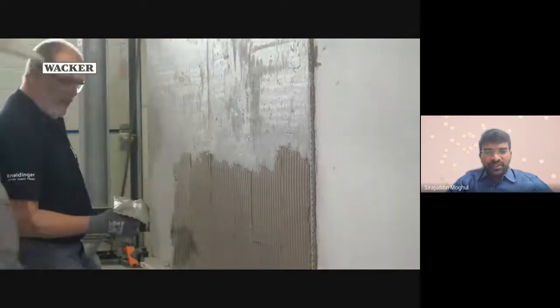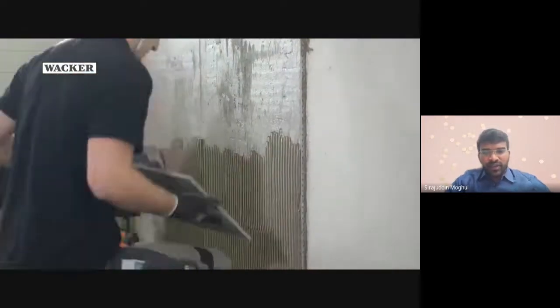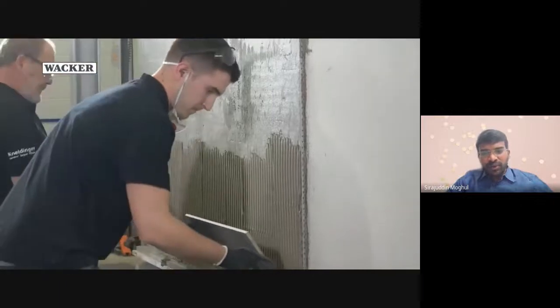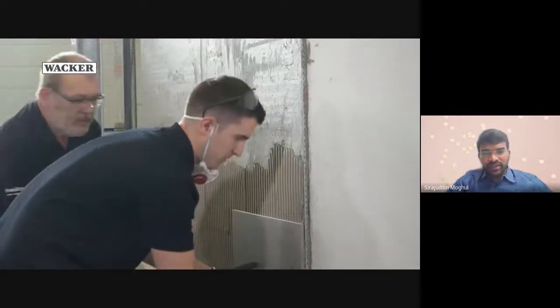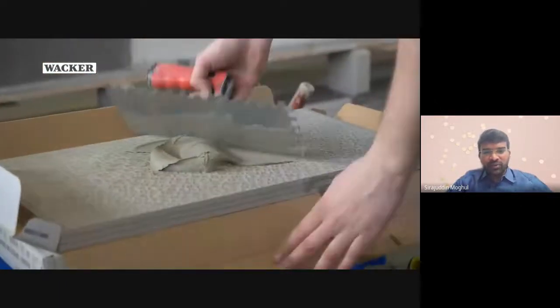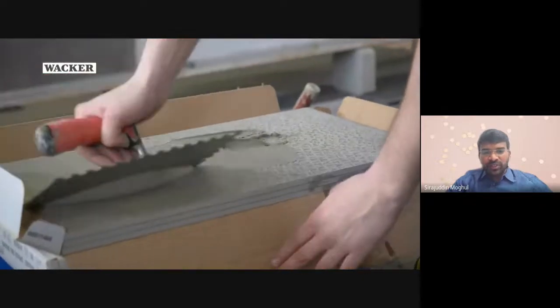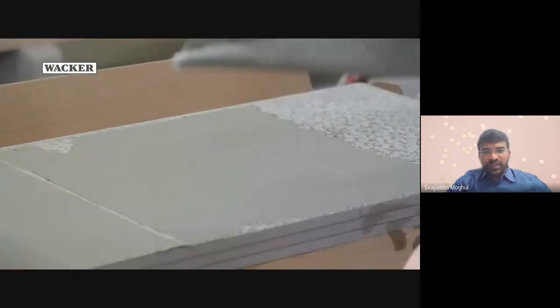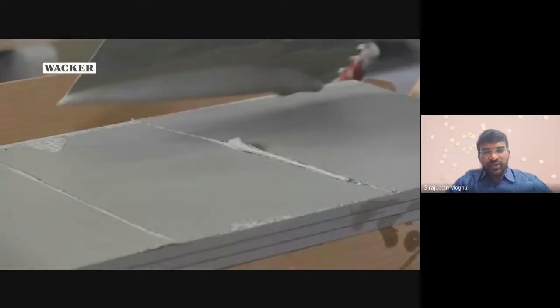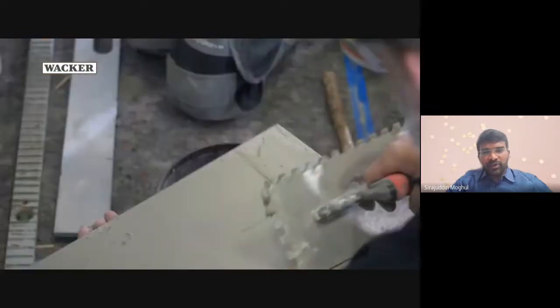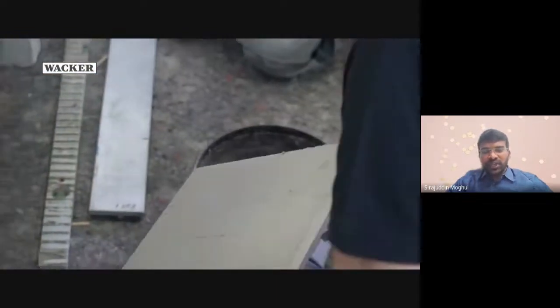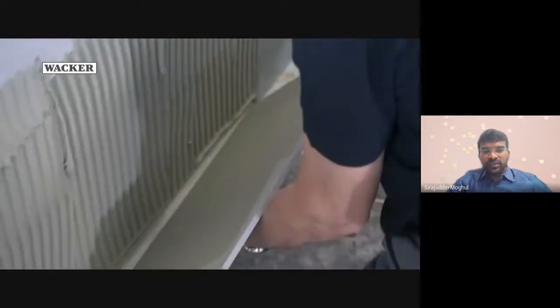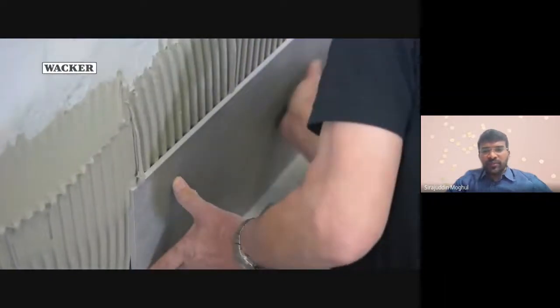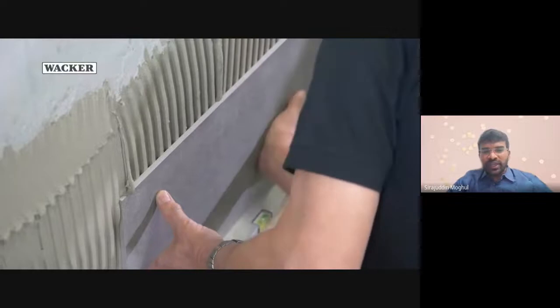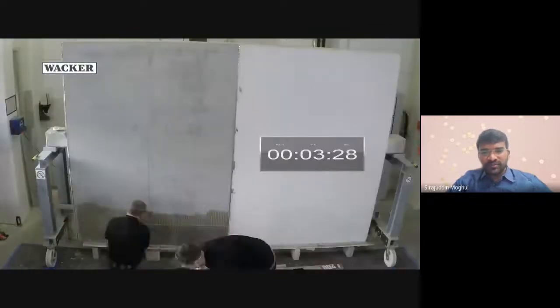And now see, this is the thin bed technology where he uses a polymer modified mortar to apply tiles. You apply the mortar with a trowel, draw notches, and do back buttering onto the tile. Back buttering is needed only when the size of the tiles is very big. And now the tiling work is done.